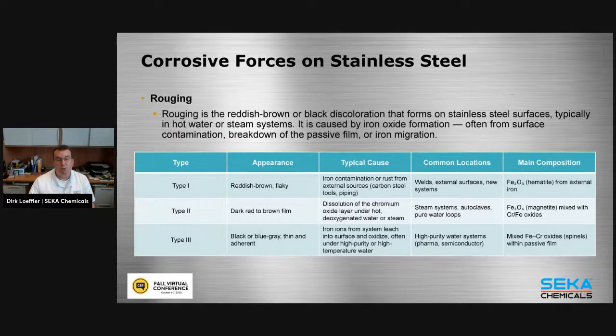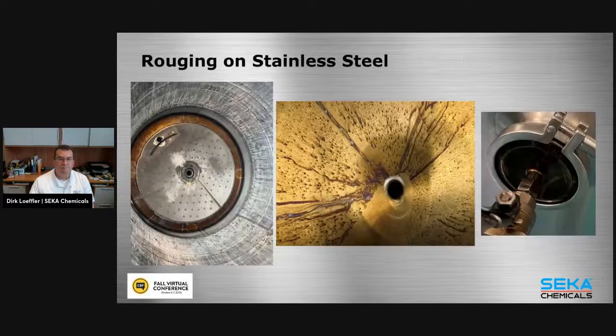Type 3, the worst kind, unfortunately: black, blue-gray, thin and very adherent. Here, generally, what we have is poor quality stainless steel and high temperature applications. So we find this in brew kettles, hot liquor tanks, and in systems that haven't been properly passivated, or the owner didn't know that the equipment was such poor quality. We're looking at spinels here.